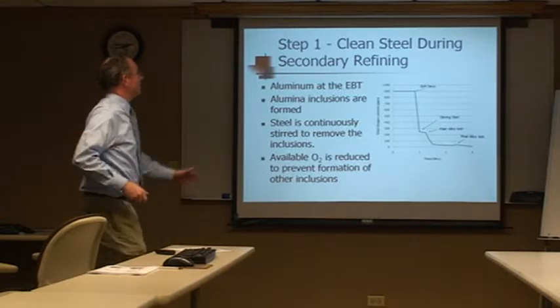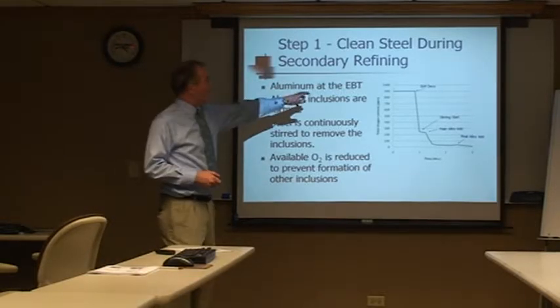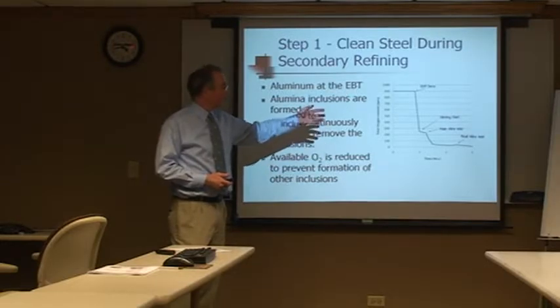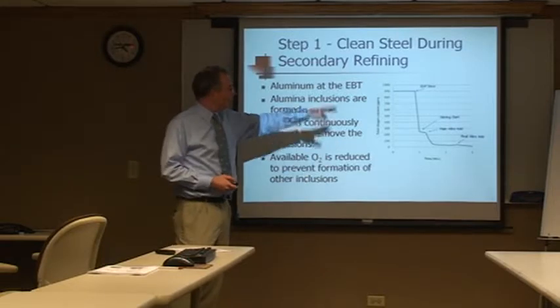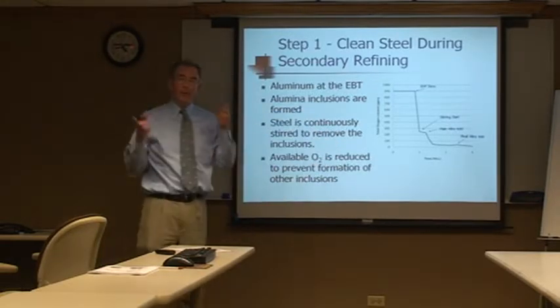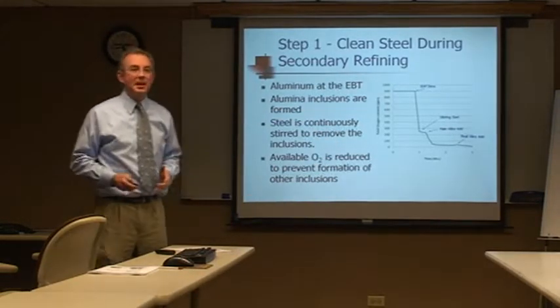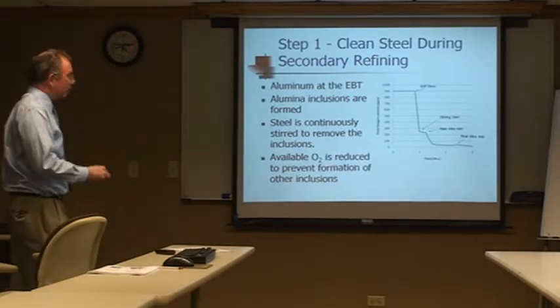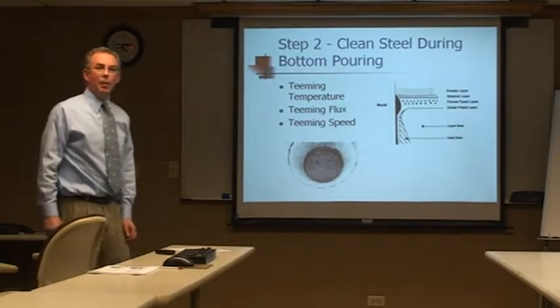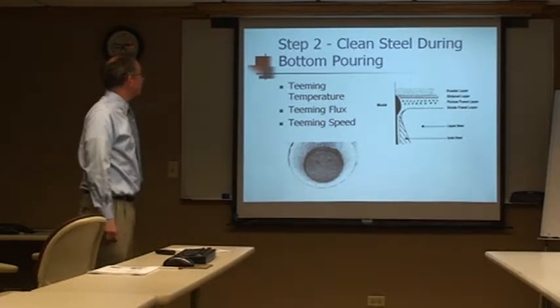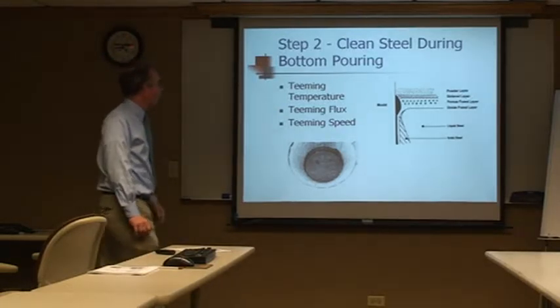So the good news is we started off with high oxygen. We added aluminum to make Al2O3 alumina. Now we're stirring the alumina out, and as we stir the alumina out, the overall oxygen content comes out. So now we have a ladle full of clean steel. Now what we have to do is get it into the molds without having any problems.